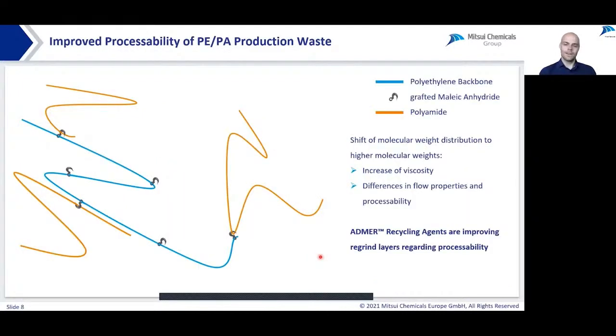But first of all, let's have a look at what is happening during compatibilization regarding molecular weight. The MAH grafted PE bonds to the PA molecules, and this results in an increase of molecular weight and a shift of molecular weight distribution. Consequently, the viscosity goes up and you will gain different flow properties.